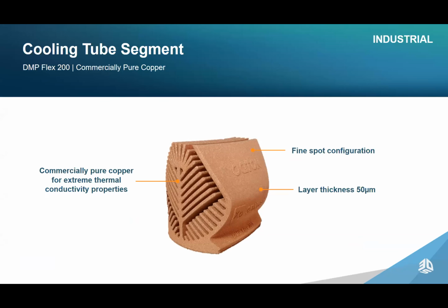Yeah, so with commercially pure copper, we're absolutely seeing things like cooling tubes, and in this case, we printed on the Flex 200 fine spot configuration, with 50 micron layer thickness. And this is commercially pure copper. This was shown at IMTS, and we'll be showing it again at Formnext. It's a little cross section through a cooling tube with a heat sink inside.